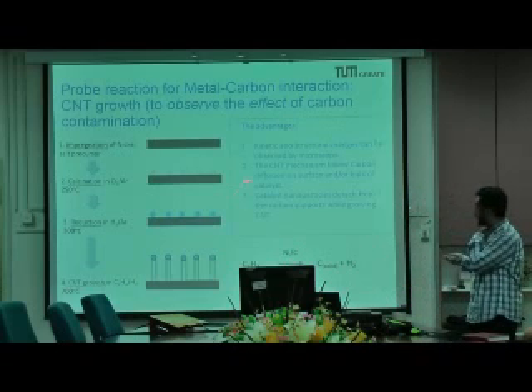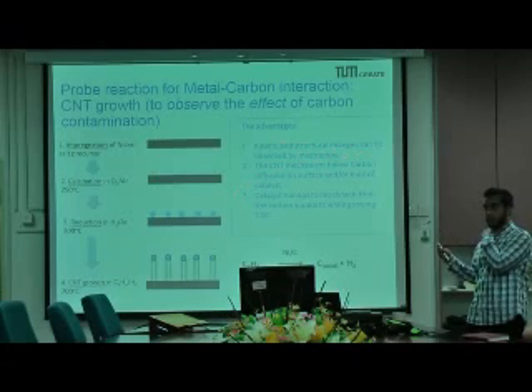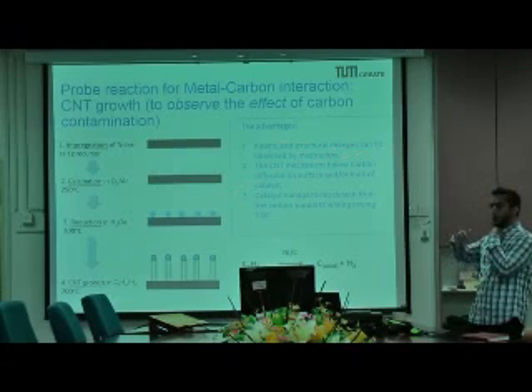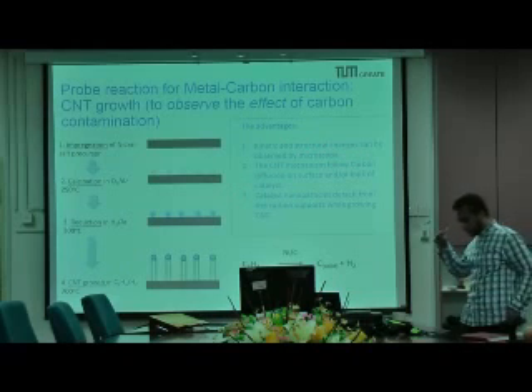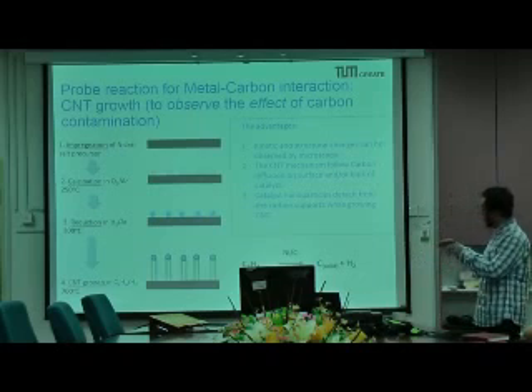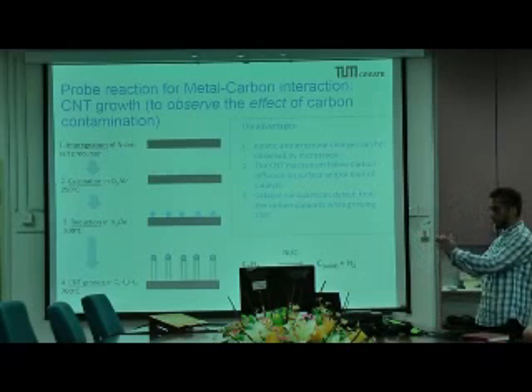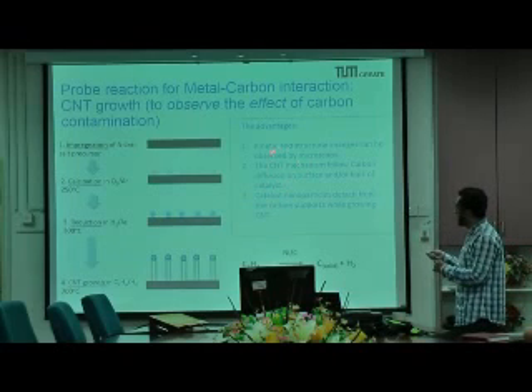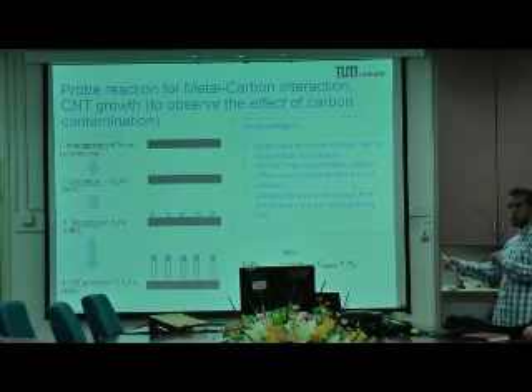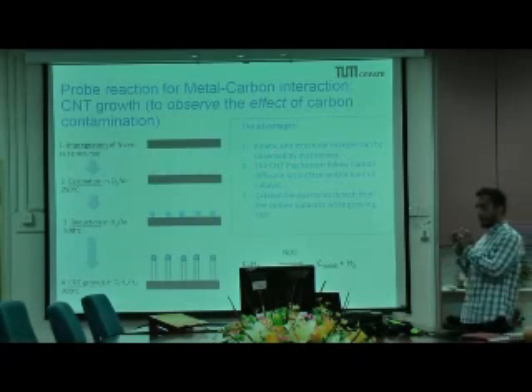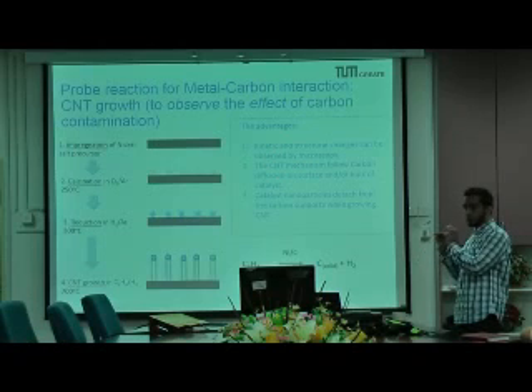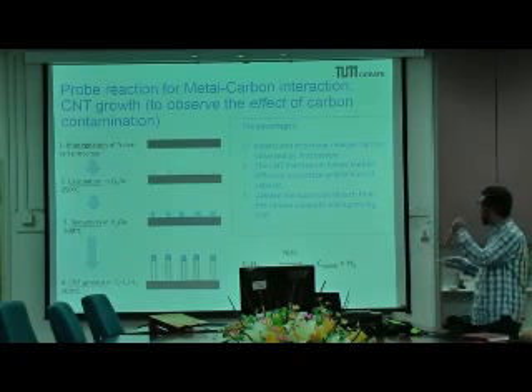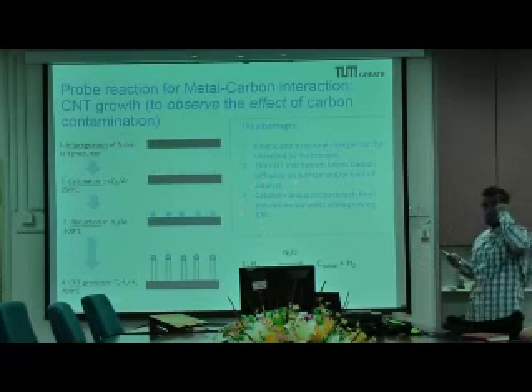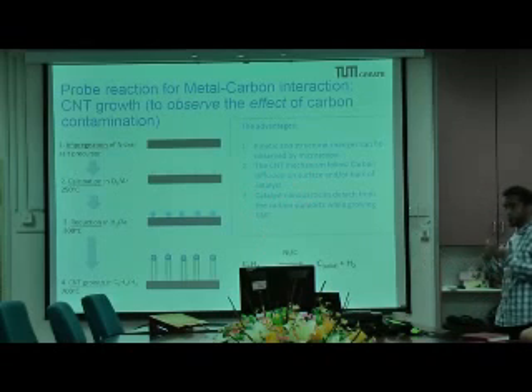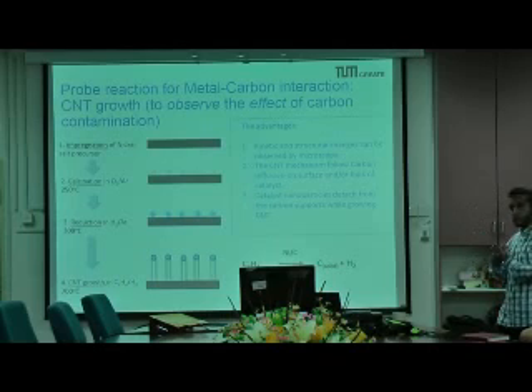The advantage is that the kinetic and structural changes of this reaction product can be observed in microscopy. Instead of getting numbers from chromatography or GC, you see the product, so it's easy to tell whether something is changing. The nanotube mechanism itself follows carbon diffusion into the substrate bulk. So if carbon contamination takes place, it will very likely disturb this very nice equilibrium. Another important thing is that the catalyst will eventually detach from the carbon surface. So this allows us to tell, once the catalyst is moved away from the carbon support, whether the influence is still there or not.